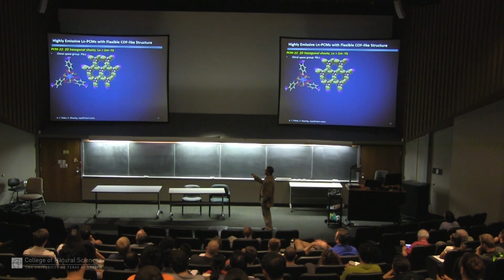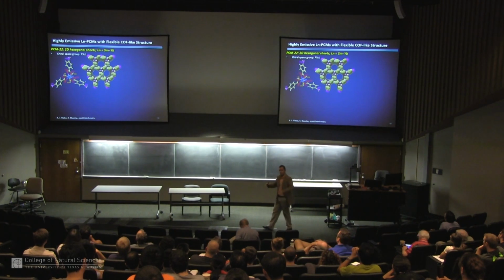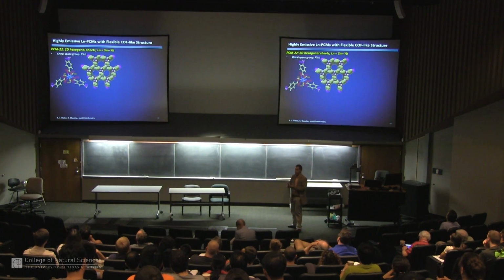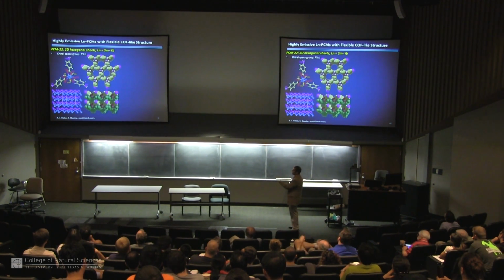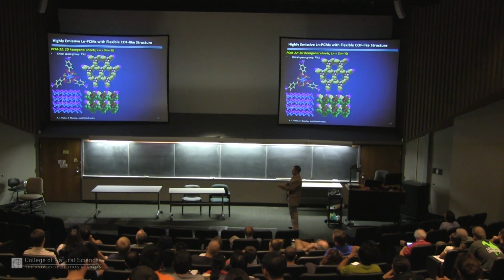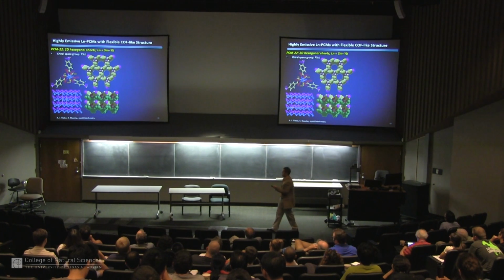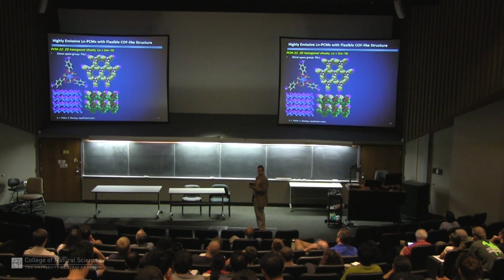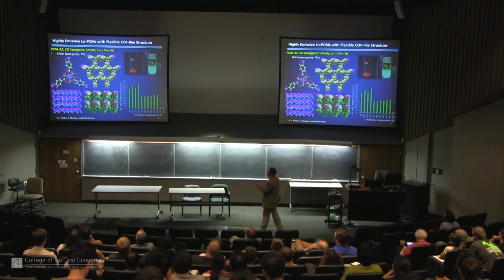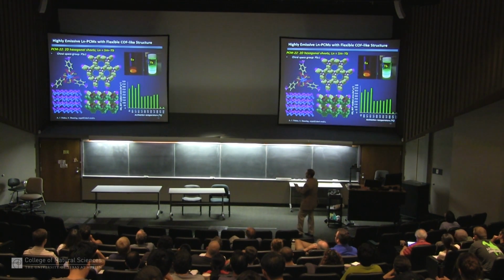It has these really big hexagonal pores, so it looks a bit like an eclipsed version of graphite. And this is interesting because it is a layered material. So in the crystal structure here, I'm showing you a layer that's packed next to the next layer, and you can see alternating layers are very tightly stacked against one another. And they're lined up in an eclipsed fashion, so you get an infinite 1D tube going through the material that you can put guest molecules into. Normally things want to stagger, just like graphite does, because they want to maximize their interactions. There's something special about this material that allows it to eclipse, which I'll show you.